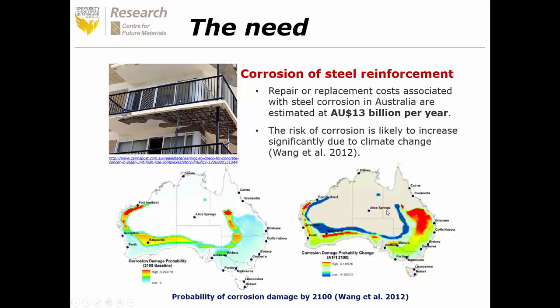So this photo shows one of the high-rise buildings on the Gold Coast, which was demolished only 20 years after it was built. And the reason for that is the significant corrosion of the steel reinforcement in its main structural components. In fact, the repair and replacement cost associated with steel corrosion in Australia is estimated at around 13 billion per year.